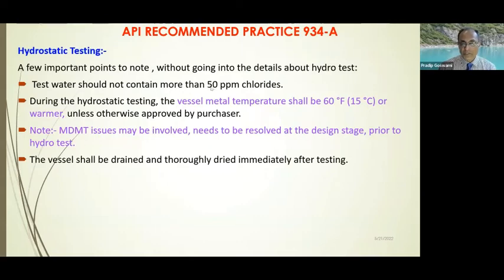And as you know, basically test water has to have a chloride limitation, should not contain more than 50 ppm of chloride. And typically, during the hydro test, the vessel metal temperature should be 15 degrees centigrade or warmer. In no way should it go below 15 degrees centigrade, or else in such a thick reactor, you can have a tendency for a ductile to brittle transition. Because as you know, hydro test exerts immense pressure, and if the temperature of the media is low, that can trigger any kind of a failure in the material. So that is why the water temperature during the hydro test has to be closely monitored, and it should be in this particular range.